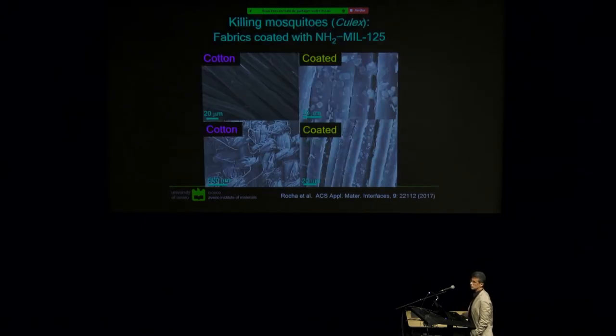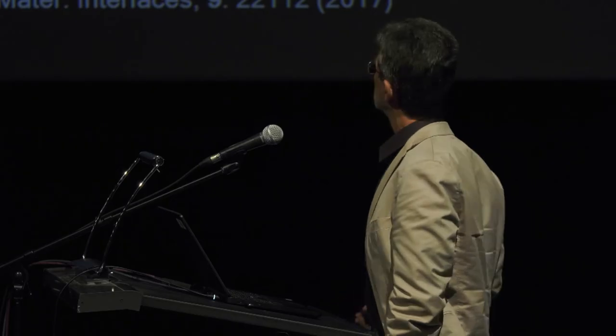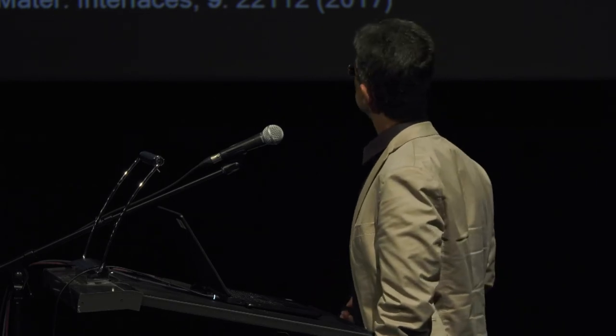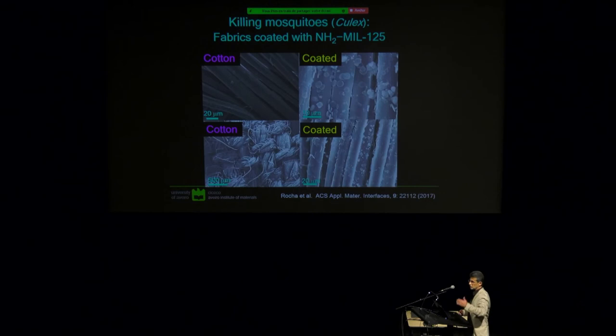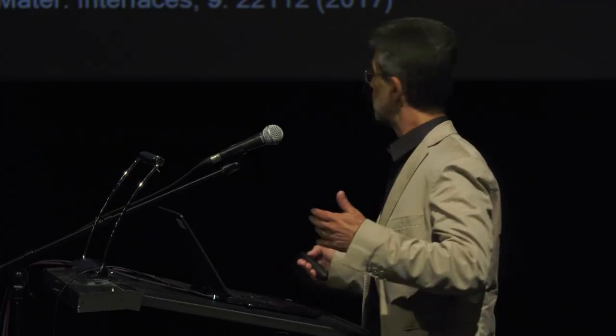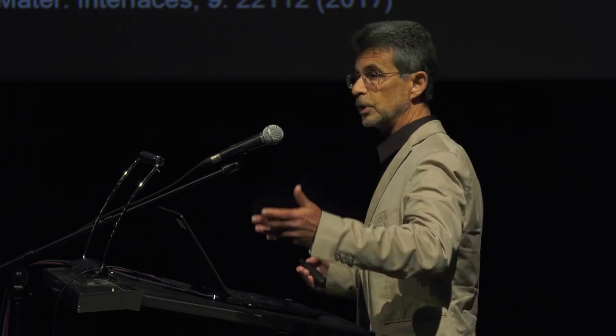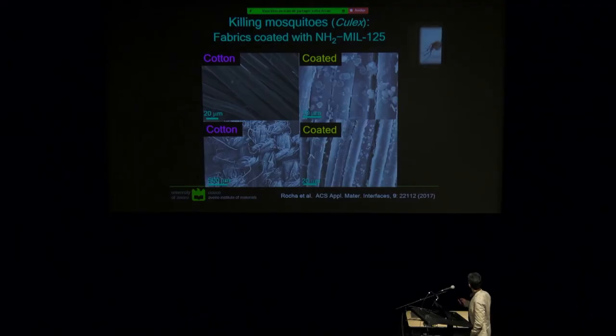And so what we decided to do was take this MOF and take some cotton or similar fabric and then coat the cotton fibers with the MOF crystals. And these are just different magnifications. You can see the little MOF crystals and the fibers. We wanted to coat these, and we wanted a chemical coating. Otherwise, this would be removed. The crystals would disappear when you wash the net, or with time. So the idea is that a mosquito lands and a mosquito dies. That's a very simple idea.